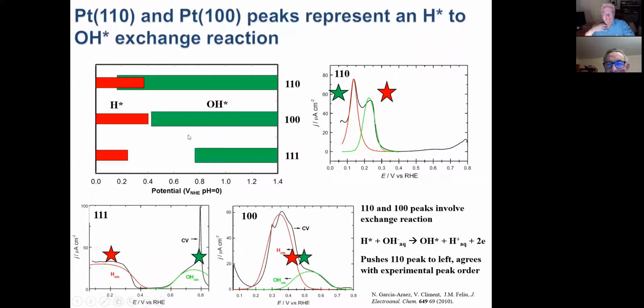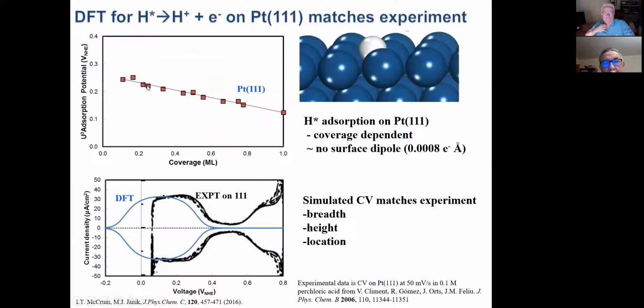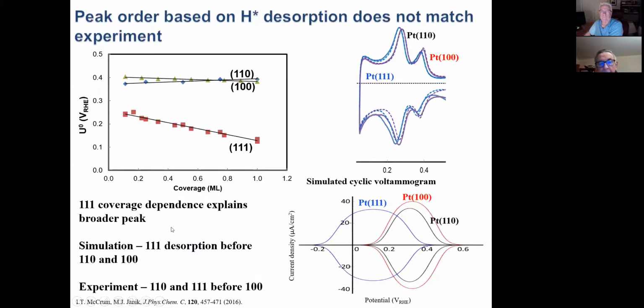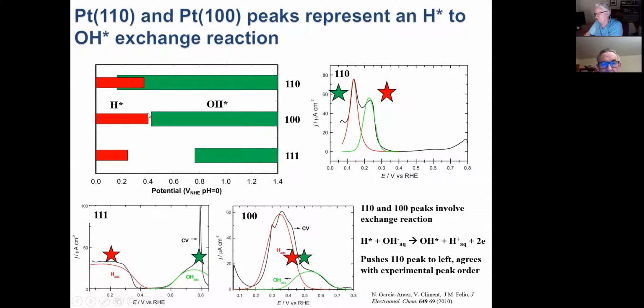But our research and our DFT calculations have suggested that on 110, the OH group actually binds quite strongly. So where this region in the cyclic voltammogram on platinum goes to a current of 0, and then OH adsorbs at a higher potential. On the other surfaces of platinum, OH binds strong enough that it can come on the surface down in this range. And our DFT calculations then say 100 is about equal. Where the hydrogen comes off, OH is going on at about the same point. And on the 110 surface, the OH would actually like to go on before the hydrogen comes off. So instead, we get an exchange reaction where the proton comes off as the OH goes on.